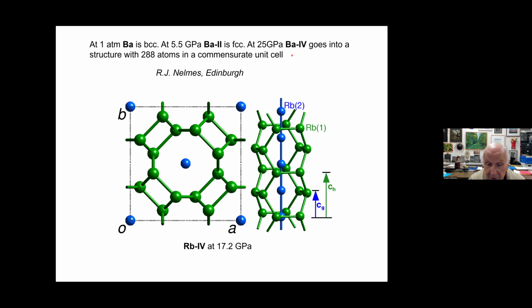Here's another one: rubidium at 17 gigapascals. That is, 17 gigapascals is just 170,000 atmospheres. Not even a million atmospheres. It goes into a structure where part of it looks like a clathrate. That's the green atoms, the rubidium atoms, which are numbered 1. And threading that clathrate-like structure is a needle of rubidium-2 atoms, which has an incommensurate cell spacing relative to the green. The blue lattice is incommensurate with the green lattice. Again, why are they doing this? Well, I don't know exactly, and I did not predict it, but actually some other people did.